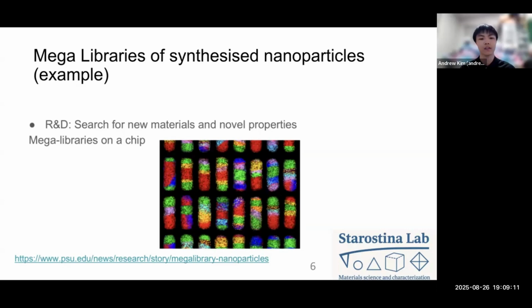By altering the reaction conditions, they can control where in the nanorod the copper is replaced: at one end of the rod, at both ends simultaneously, or in the middle. They can then repeat the process with other metals, which can also be placed at precise locations within the nanorods. By performing up to 7 sequential reactions with several different metals, they can create a veritable rainbow of particles. Over 65,000 different combinations of materials are possible.